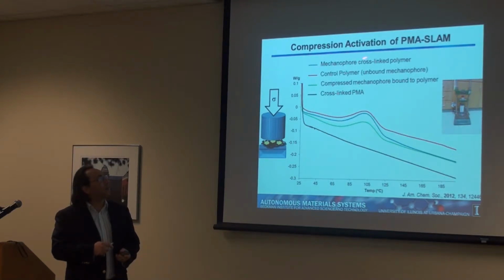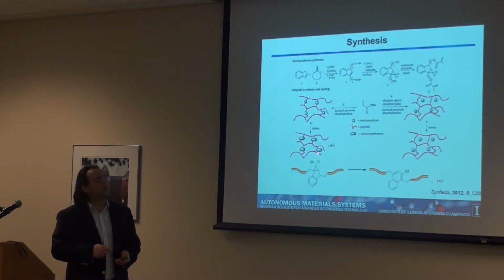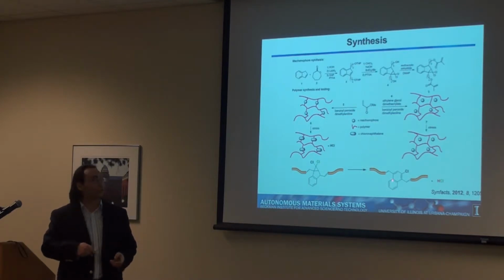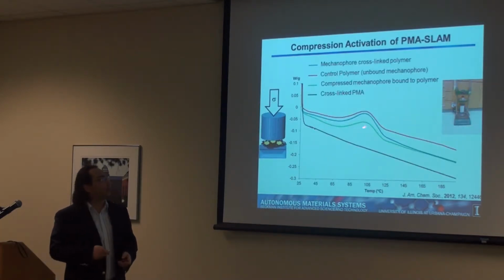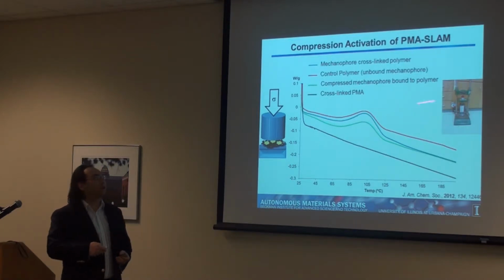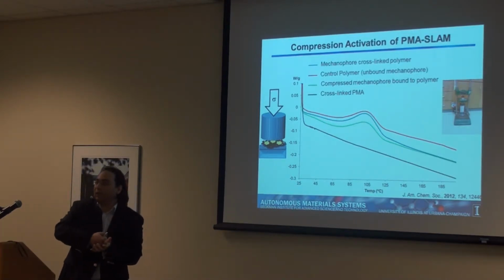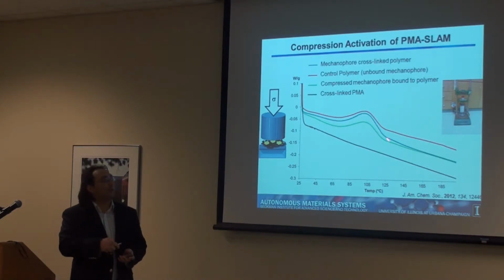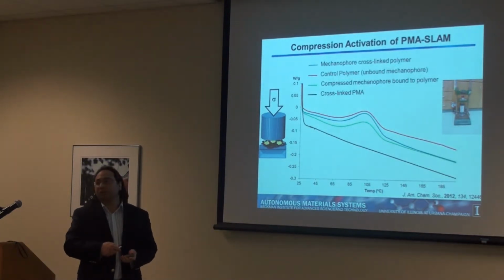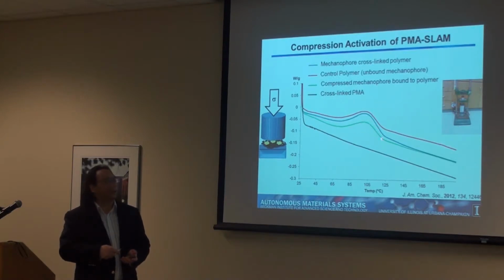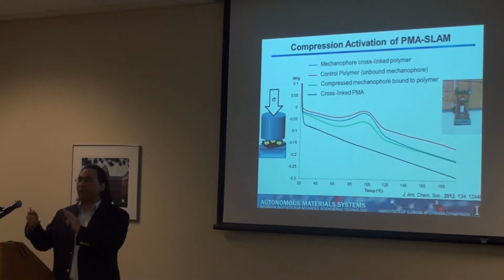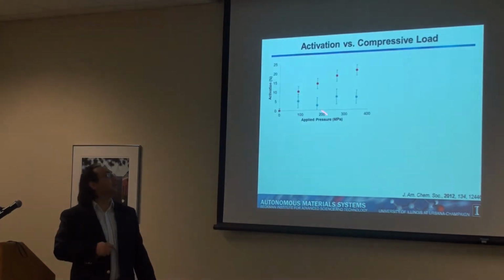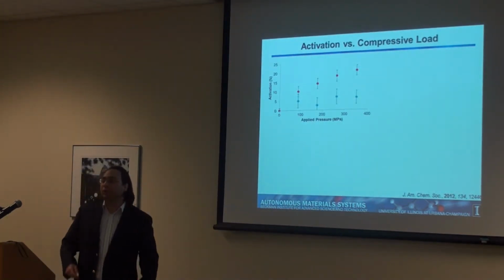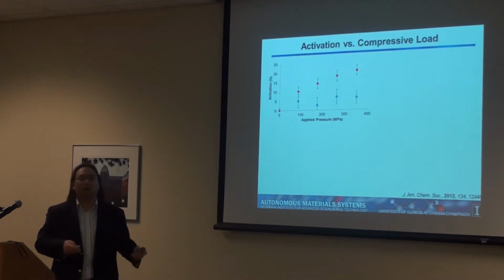So basically, for my polymer and my control polymer, I got peaks because both of them have the mechanophore in it. I have this dichlorocyclopropane. When I heat it, they undergo this reaction, release acid and energy. So basically what I do, I take the polymer, I put it in a press, apply compression, mechanical force, and then I measure this again, and I see the decrease in this peak. Then I integrate those peaks, I compare what I have afterwards to what I had before, and then you can just make a simple graph and measure how much you activated, how much of that molecule you lost.